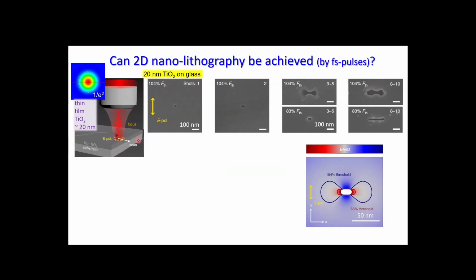So we have a transparent substrate, which is glass, and then we are depositing a titanium dioxide film, 20 nanometers, so to speak, resist. Because we can tune exactly the pulse energy so that we are ablating at the very top of the intensity profile, we can ablate a nanohole by a single shot. If we are repeating shots, we see a slightly larger ablation structure. And if we keep repeating, let's look at those images here on the top, we begin to see this kind of dipole looking